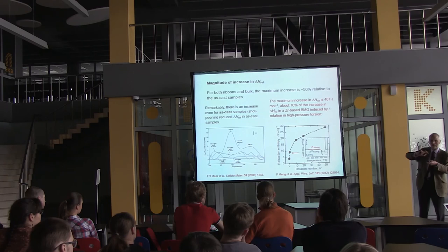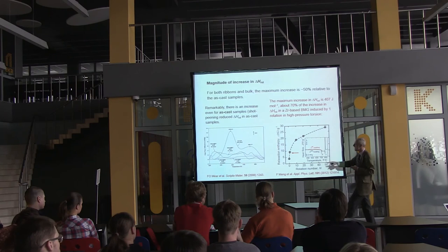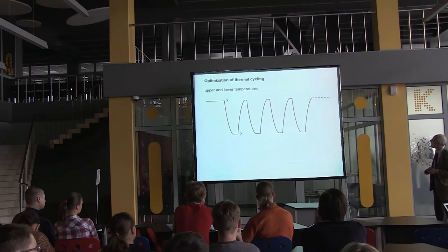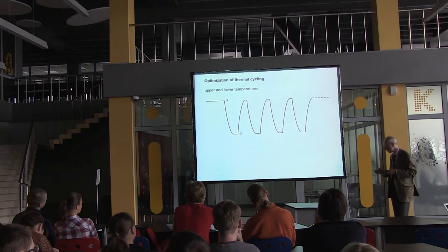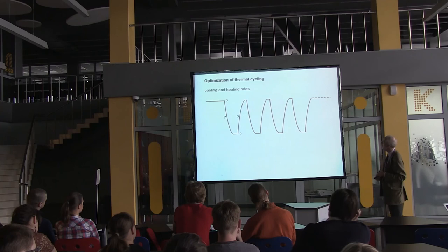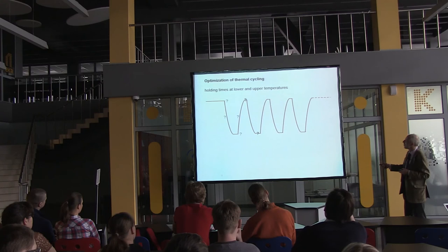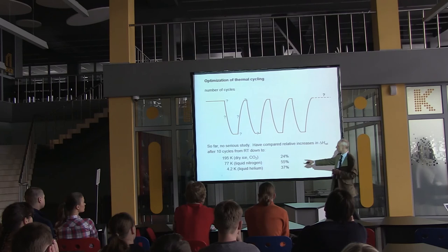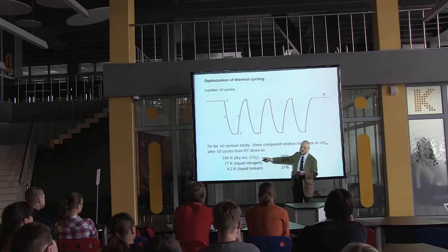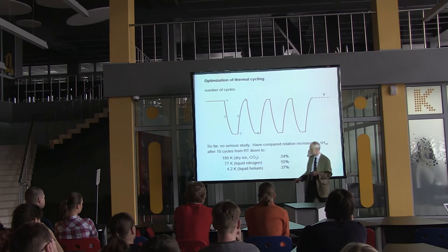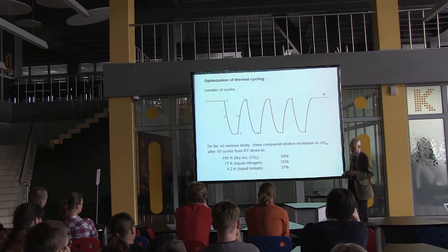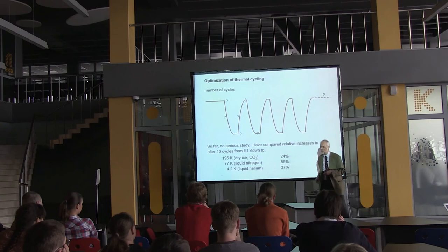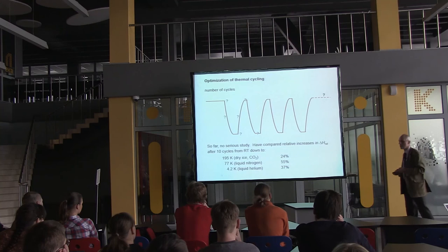That seems remarkable: high pressure torsion is a very major deformation, yet it puts in the same energy as temperature cycling to liquid nitrogen. Of course, we have done very simple experiments and have not optimized the temperatures, heating/cooling rates, or holding times. We have done a little work on the optimum low temperature — liquid nitrogen, solid CO2, or liquid helium. Initial measurements suggest it may be optimum around the liquid nitrogen point, and liquid nitrogen is extremely easy to use — which is why we based our experiments on it.